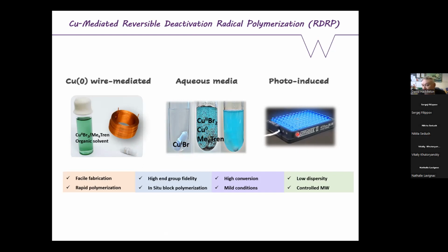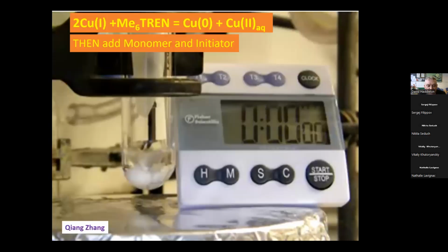And photo-induced, we use copper 2. So we pretty rarely use copper 1 anymore. And when we use copper 2, we use these LED arrays, which we like a lot. And I'll come back onto that, where we photo-reduce copper 2 to copper 1. Copper 1 then disproportionates to copper 0 and copper 2, and the chemistry progresses. So I'll start with the aqueous media and why I think this is quite good.